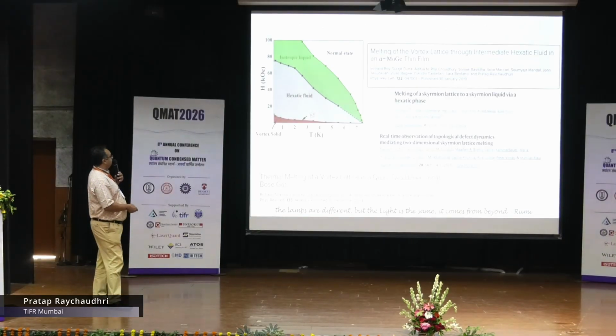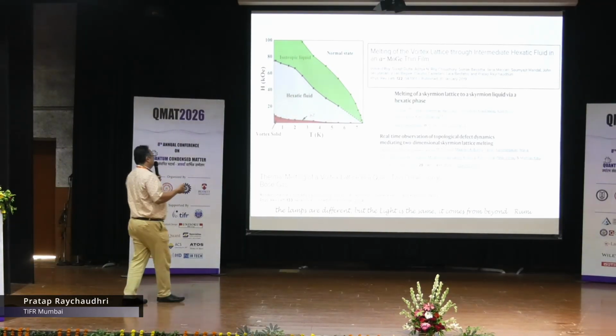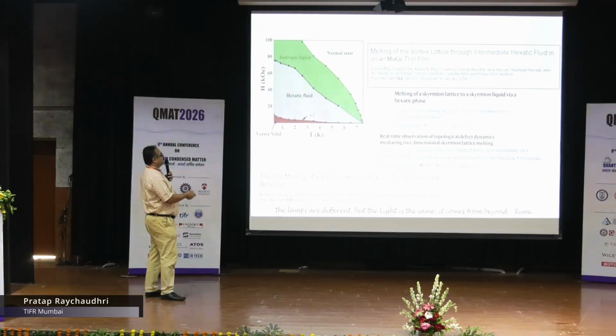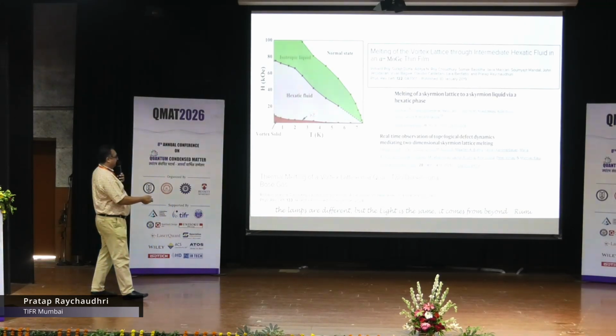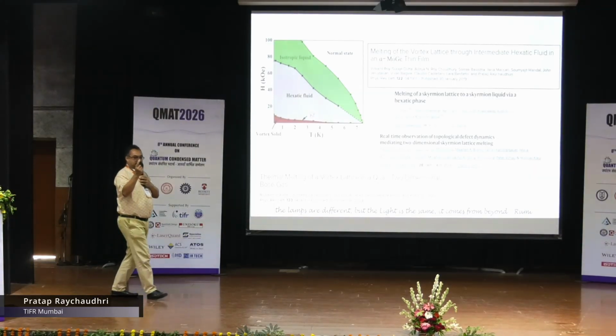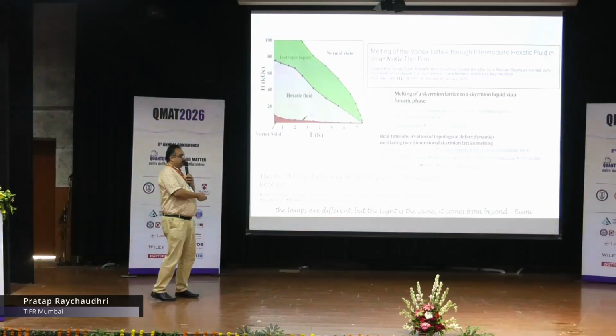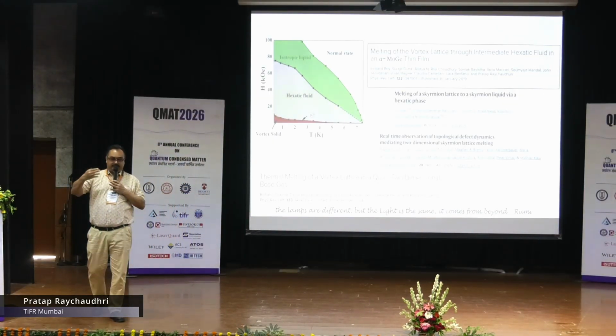Why are these kind of studies important? Very soon after we found this in a vortex system, exactly the same sequence of transformations with essentially the same analysis was found from Lorentz microscopy in a Skyrmion lattice. Then this was again refound by another group who studied it in more detail. It was also found in the vortex lattice in a rotating Bose-Einstein condensate. So what I want to say is that the vortex system often provides you a platform to study phenomena that later can be investigated in more complex systems.